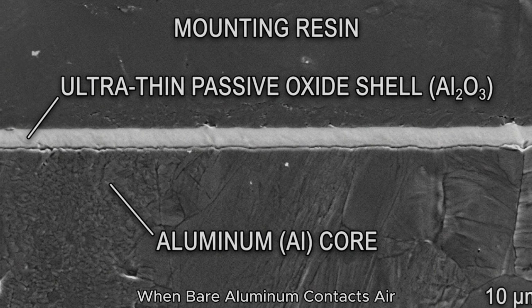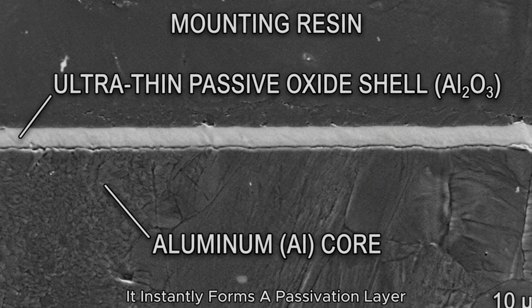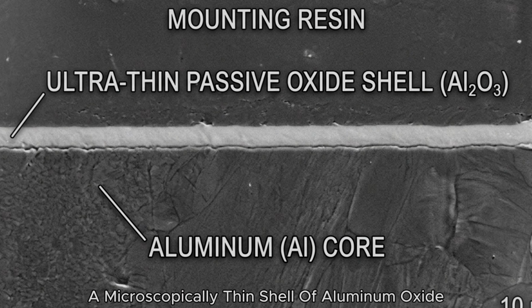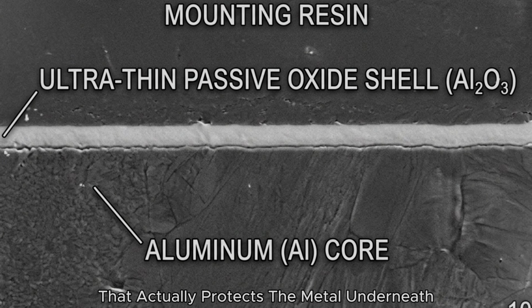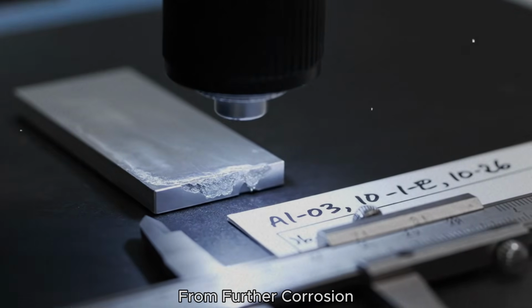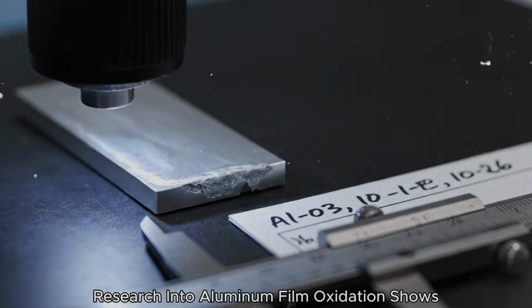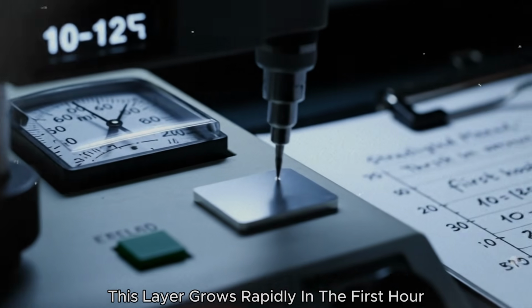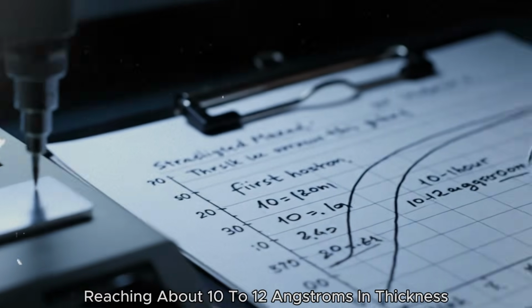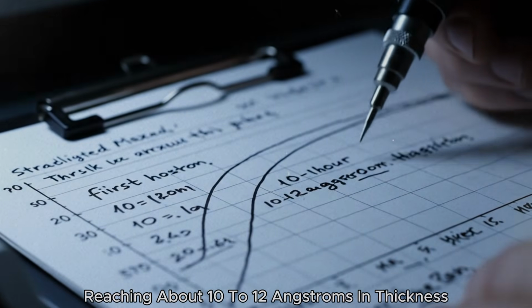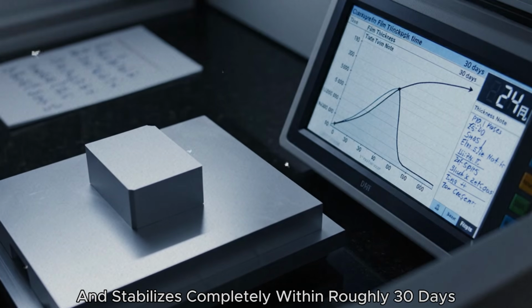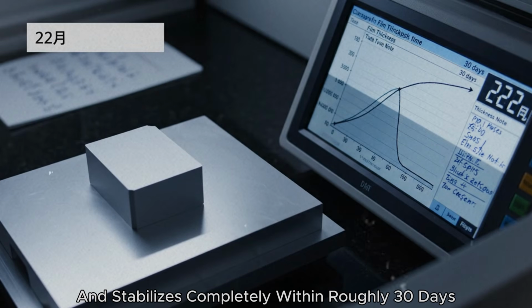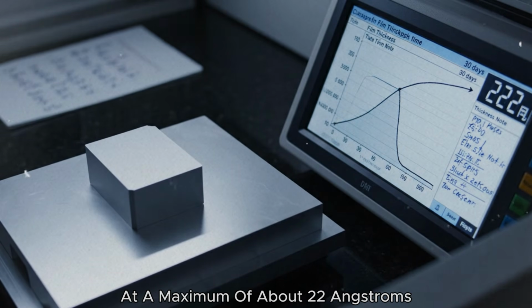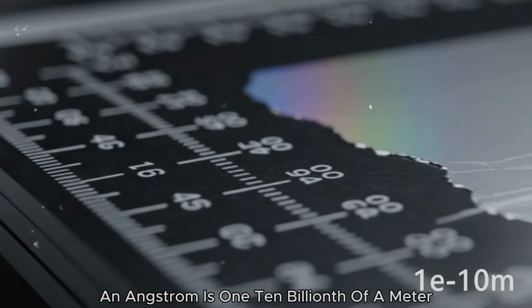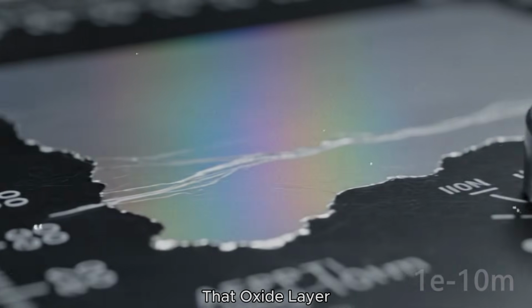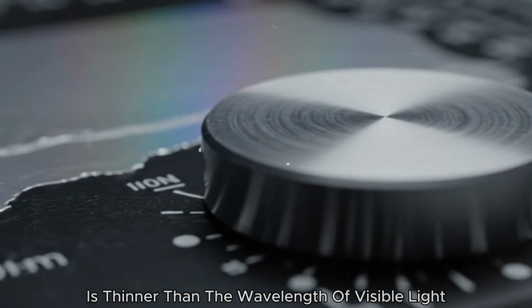When bare aluminum contacts air, it instantly forms a passivation layer, a microscopically thin shell of aluminum oxide that actually protects the metal underneath from further corrosion. Research into aluminum film oxidation shows this layer grows rapidly in the first hour, reaching about 10 to 12 angstroms in thickness, then slows dramatically and stabilizes completely within roughly 30 days at a maximum of about 22 angstroms. An angstrom is 1/10,000,000,000th of a meter. That oxide layer is thinner than the wavelength of visible light.